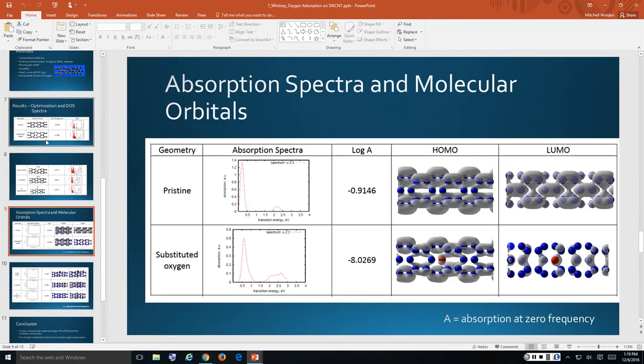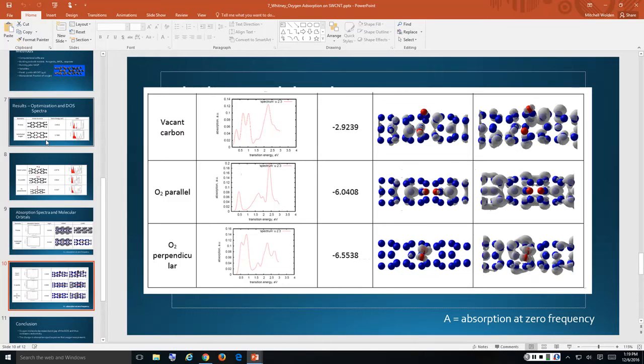So for the HOMO and LUMO, it does not change a lot except for this one. It has localized orbitals on the oxygen. In which case, when you substitute or when? No, the one that I put on top, just the normal one. So when it's physically absorbed, then you have very strongly localized orbitals, and these orbitals introduce these states inside the gap, right? In the other cases, when it's substituted, it's more delocalized over the surface, although the gap is still changing. Okay, so you have a different nature of these electronic states. Okay. Thank you. Dr. Khan?